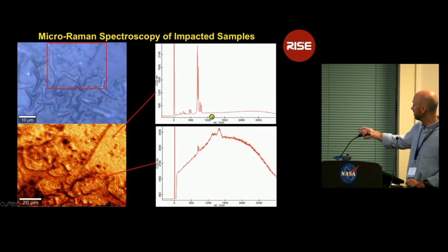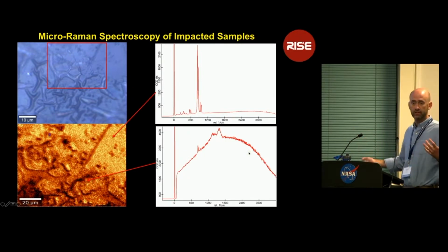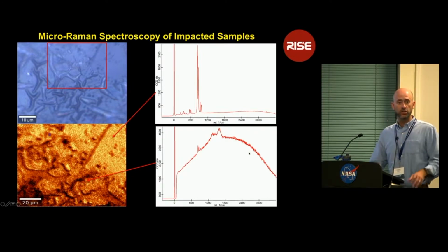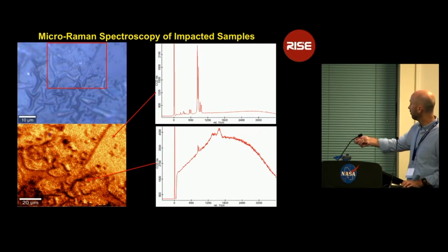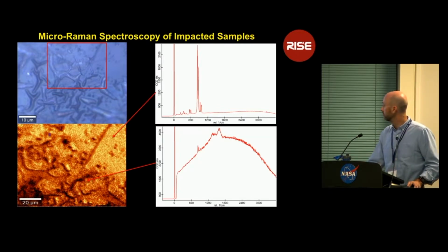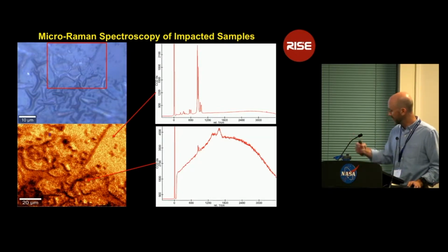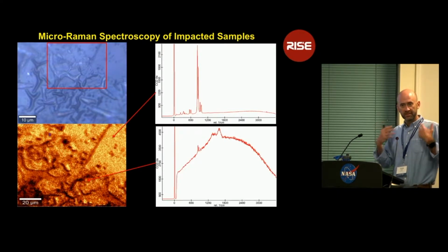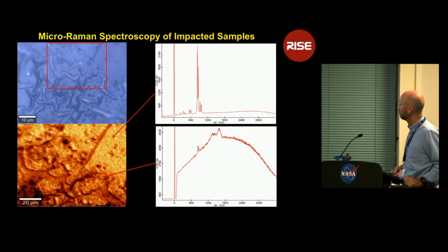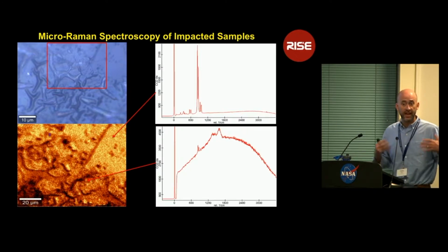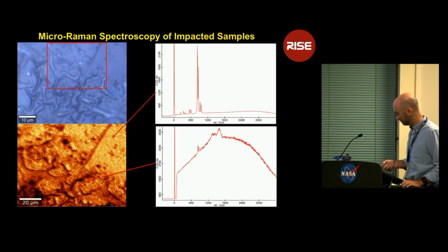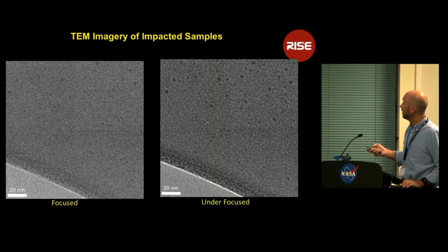we've induced a lot of fluorescence in the sample, which is often something that you see when you introduce amorphous material into a Raman spectrometer. We also see these D and G carbon bands here, which are due to the carbon that was in the projectile. But we're seeing both the damage and structural changes at a variety of spatial scales, which is the point here.